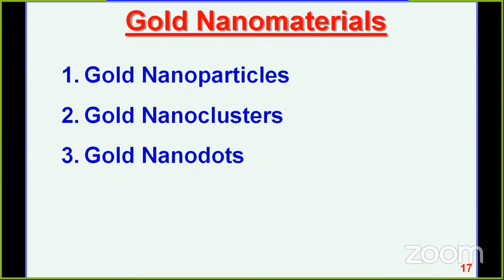One important question people can ask: gold nanoparticles have oxidation state zero, silver nanoparticles have oxidation state zero, but is it possible to prepare iron oxidation state 0 nanoparticles, zinc 0 nanoparticles, or titanium 0 nanoparticles? Yes, it is possible, but it is not stable. Even within minutes, that iron 0 becomes iron 2 plus or iron 3 plus. That is why it is called an iron oxide nanoparticle. That kind of material is called a metal oxide nanoparticle.